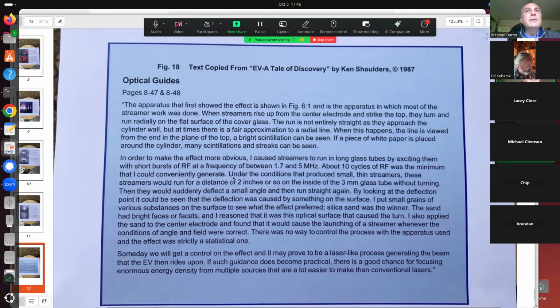conveniently generate. Under the conditions that produce small, thin streamers, these streamers would run for a distance of 2 inches or so on the inside of a 3 millimeter glass tube without turning. They then would suddenly deflect a small angle and then run straight again. By looking at the deflection point, it could be seen that the deflection was caused by something on the surface. I put small grains of various substances on the surface to see what the effect preferred. Silica sand was the winner.